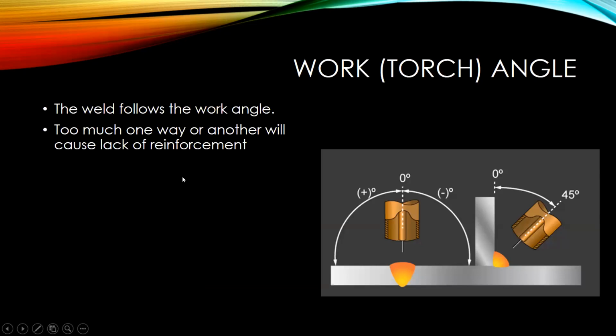Next one I want to talk about was work angle or torch angle. And the thing to keep in mind is where you point the wire, the weld will follow. So as you can see in the fillet weld that we have here, brought in at a 45, it'll wash that weld puddle up onto the top plate and the bottom plate 50-50, which is what you want. Now when we're doing a butt joint like this one, want to come in so you're perpendicular to the plate, and then it'll wash onto both pieces. If you were more positive or negative, you'd see that weld build up on one side or the other.